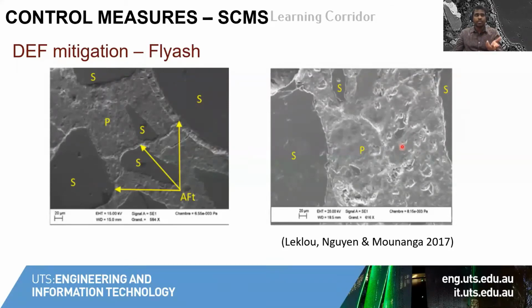So what actually contributes to this? Fly ash has a lot of amorphous silica in it, which can react with calcium hydroxide, portlandite, in the cementitious system, which is a porous hydrate. It converts that porous hydrate into more calcium silicate hydrate precipitation, which is a much denser hydrate, making the concrete relatively denser. So what is the advantage? To precipitate ettringite in the system, we need sulfates and aluminates to react with monosulfates. The movement of these sulfates and aluminates through the microstructure is restricted, because concrete with fly ash substitution has a denser microstructure due to relatively higher calcium silicate hydrate precipitation. So this is also one way of controlling delayed ettringite formation.